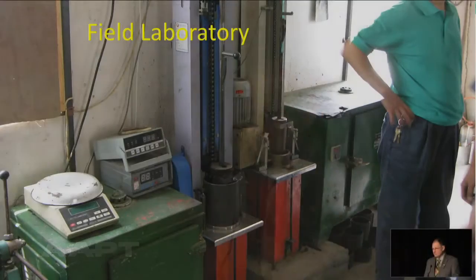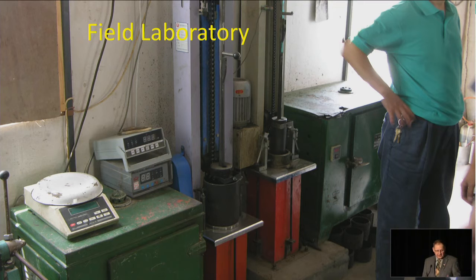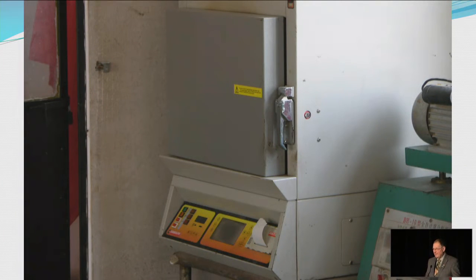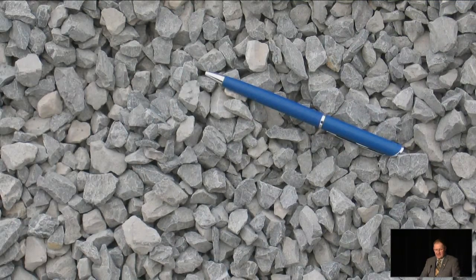Field laboratory was kind of like you'd expect to see in a lot of places. This was Marshall mix design that they were using. You can see the Marshall hammer there and some scales. They were using an NCAT burn-off oven for evaluating asphalt content.